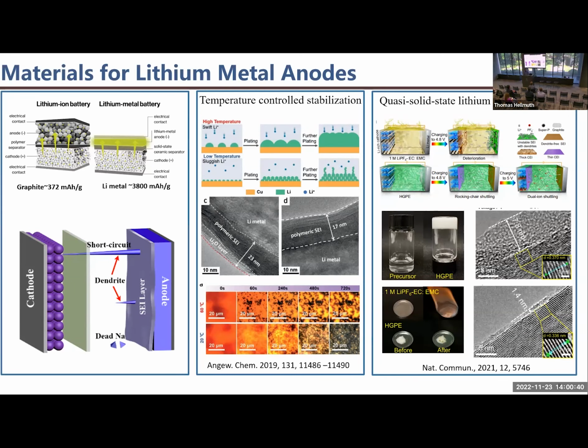Moving on, our group is also working on metal batteries, metal anodes. Now, these are different from traditional anode materials like graphite or the materials which I just introduced. If you see this figure, you can see that graphite can deliver 372 milliampere hour per gram. In comparison, lithium metal anode can deliver 3,800 milliampere hour per gram. This is nearly 10 times higher than graphite. So if this one can be utilized, this could improve performance to a much higher level.